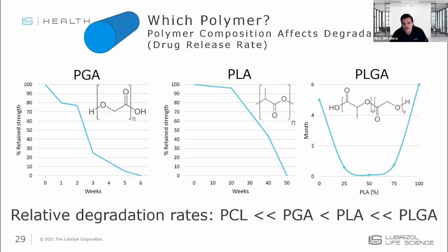And then the last consideration I'll talk about in development is with regards to bioresorbable polymers. I mentioned earlier that PLGA is one of the more common polymers in this space. This is a copolymer of polyglycolic acid and polylactic acid. If you look at polyglycolic acid, this is a polymer that degrades relatively quickly. Within 10 weeks, it loses most of its strength, whereas polylactic acid lasts much longer, degrades at a much slower rate. And again, similar to a TPU, by changing the ratios of these components, the lactic acid component and the glycolic acid component, as well as the molecular weight of the PLGAs, you can achieve different degradation rates in the body. So just another way to customize these materials using polymer selection.